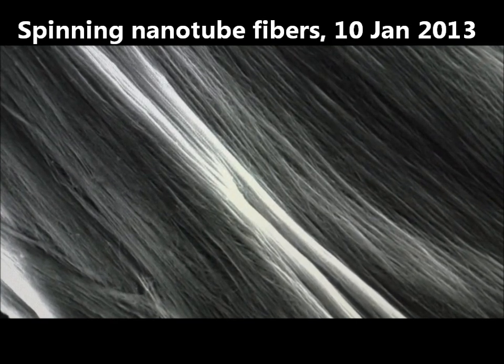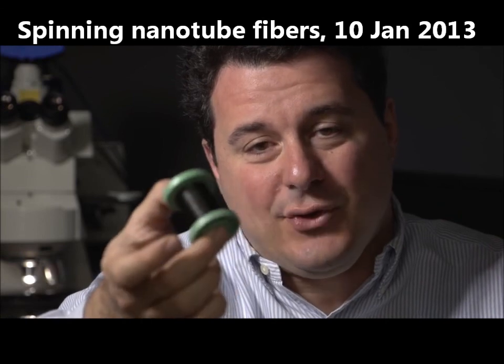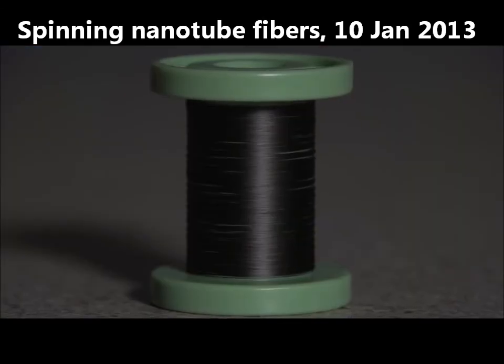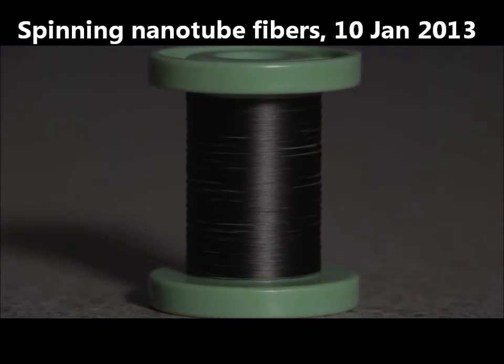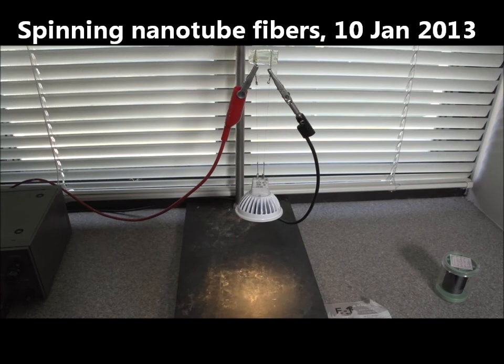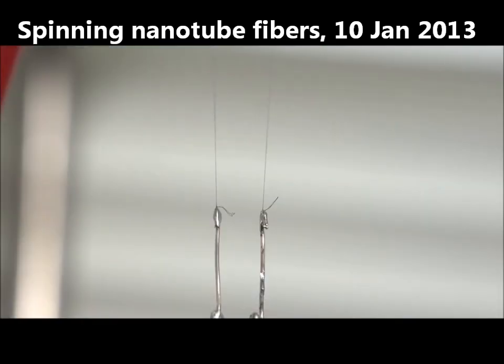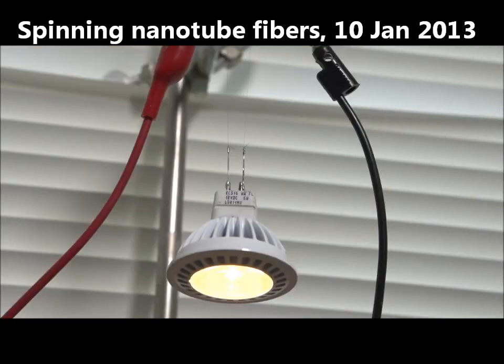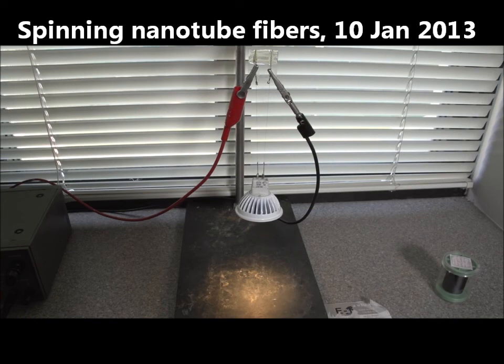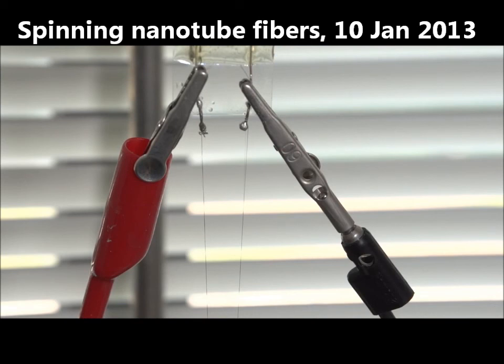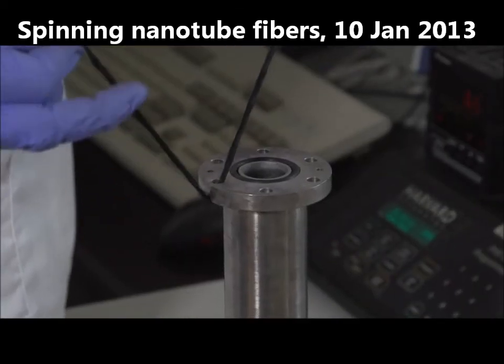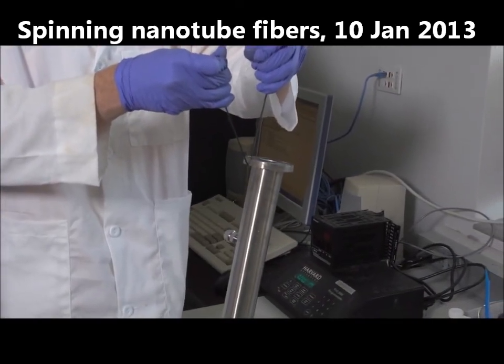Because of this structure, we can now translate the amazing properties of carbon nanotubes, which are nanoscale properties, onto an engineering fiber, which is something we can handle on the macroscopic engineering scale for applications. What you're looking at here is 2 bundles of our nanotube fiber that are holding up an LED light bulb that weighs 50 grams. Those fibers are also being used to run the current that's powering the bulb. This demonstrates the multifunctionality of the fibers: they are strong enough to support the weight of the bulb and also have high enough conductivity to provide the current. This is just some fiber that I took off the drum, which was not under controlled conditions, but it's still good fiber. We don't know exactly what the conditions were, so we don't keep it. But you can see that it has a lot of strength.